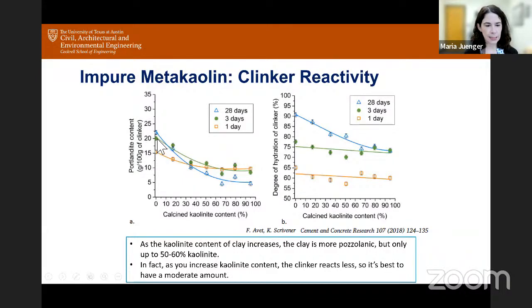What becomes really clear is that the consumption of calcium hydroxide by the SCM pretty much tails off at 50 or 60%. There's no reason to ever go higher than that because you're not able to consume more calcium hydroxide in that system. You hit a wall. The other thing to note that I think is even more important is this degree of hydration of clinker versus calcined kaolinite content. If you look at the 28-day data, as you increase kaolinite content, your degree of hydration of clinker reduces. So you're actually not optimizing your system. You're actually reducing the